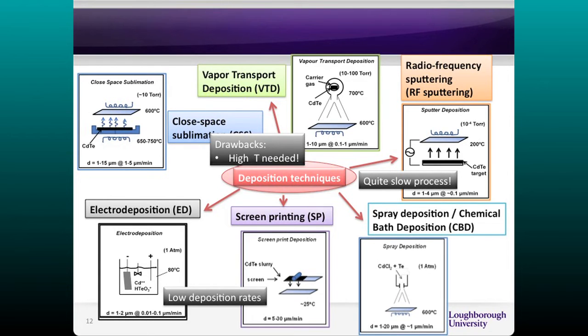We can choose, actually, among different deposition techniques. In particular, talking about high vacuum systems, we have the closed space sublimation, the vapor transport deposition, and the conventional sputtering, which is the radio frequency RF. But they show particular drawbacks, which are related to the high temperature needed, and these are quite slow processes. On the other side, we have non-vacuum techniques, and we can choose among electrodeposition, screen printing, and chemical bath deposition or spray deposition. But, as I said, we have drawbacks, and in particular for this kind of technologies, the deposition rates are extremely low.